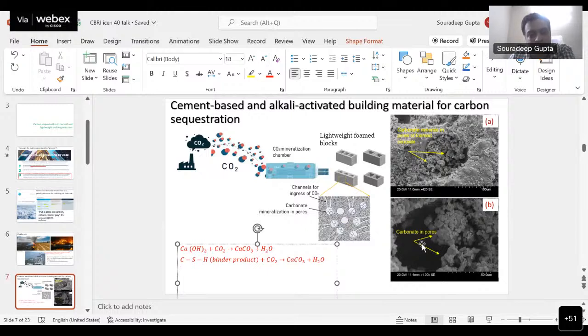But something we should take note of here is that CaCO3, or calcium carbonate, can be formed from carbonation of calcium hydroxide and calcium silicate hydrate. But we really want to minimize the carbonation of calcium silicate hydrate so that we avoid the problem of instability or degradation of the binder gel, which is associated with loss of strength. So maximizing CO2 capture through carbonation of calcium hydroxide should be the preferable pathway when you are talking about carbon capture in cementitious building materials.